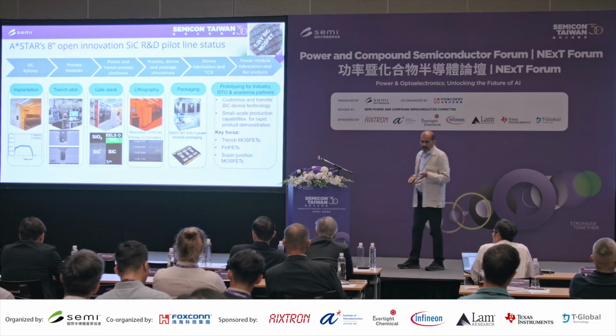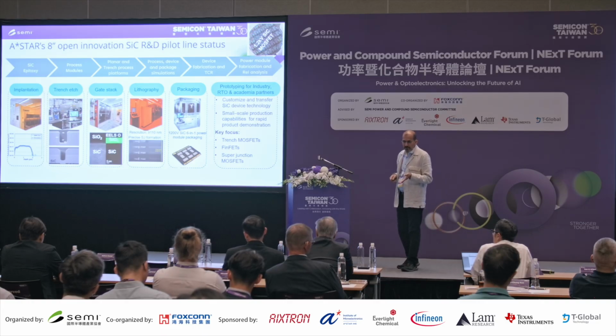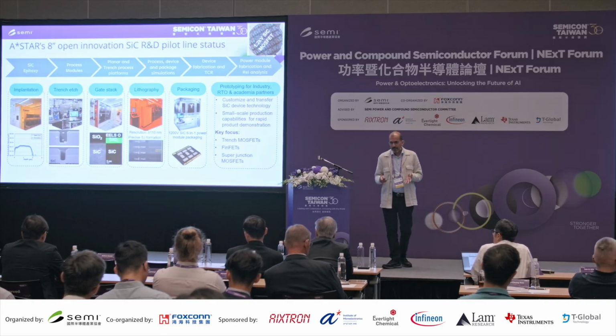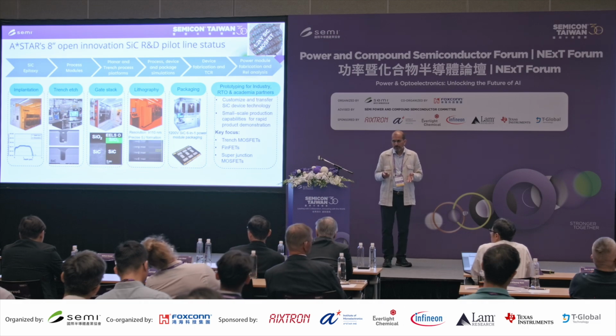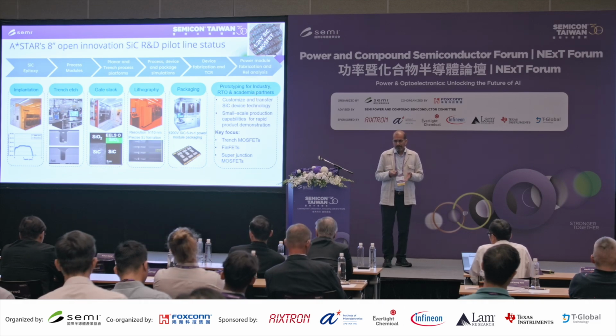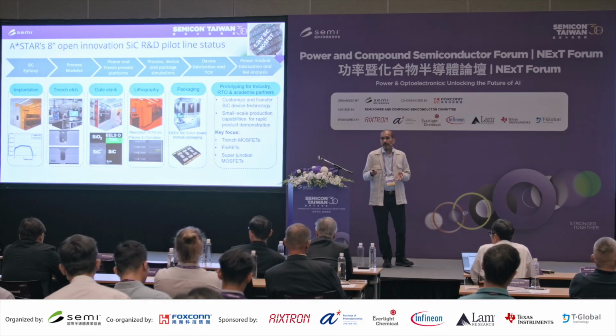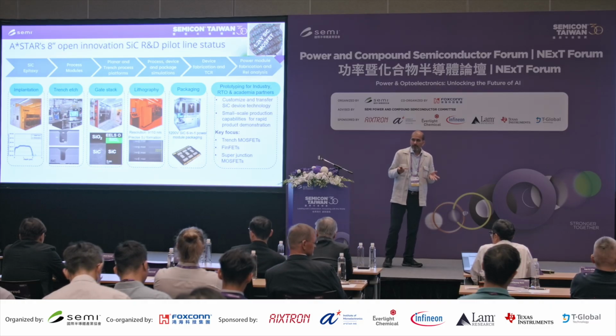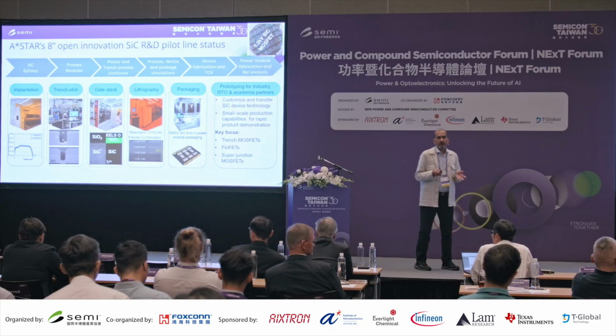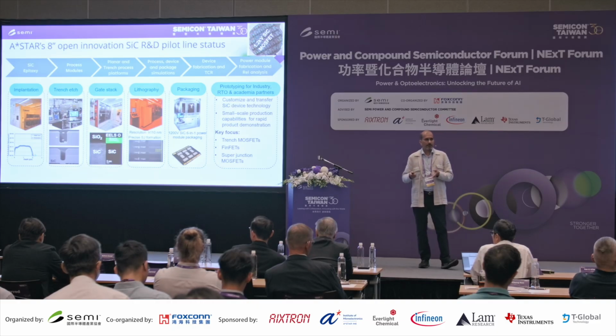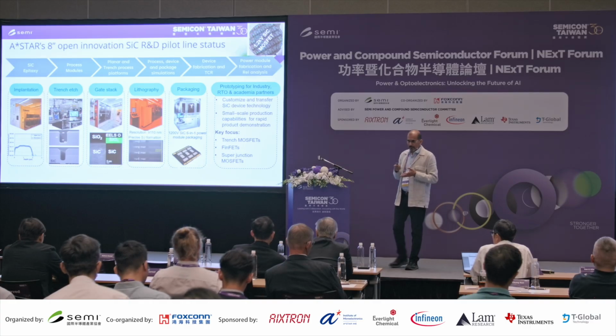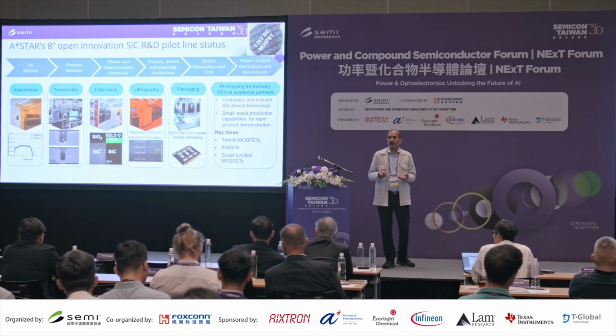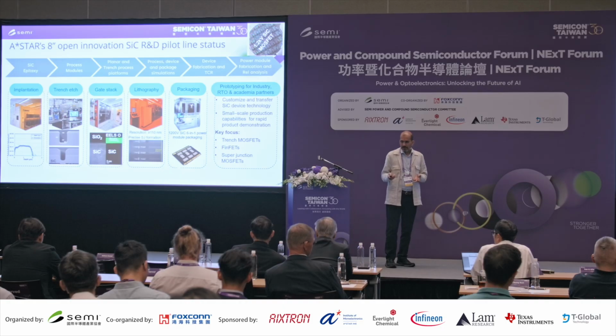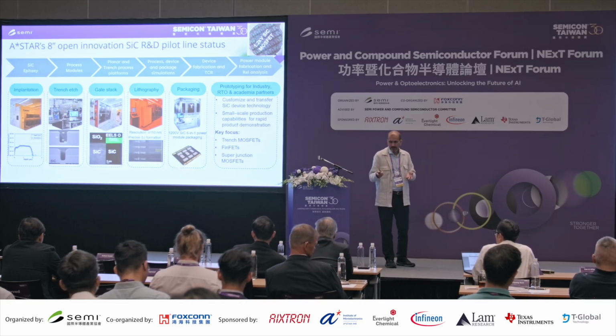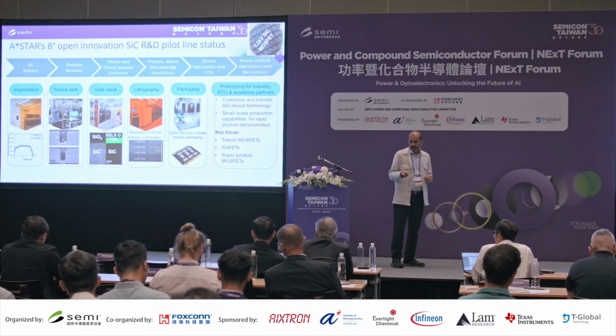For the trench, you can see here we have developed a trench with very rounded corners. For the interface, we have optimized the process such that our interface is extremely sharp. Not only conventional planar or trench gate MOSFETs, we are also developing superjunction MOSFETs, and for that we have developed a very innovative alignment scheme, and you can see here the columns are aligned very nicely.